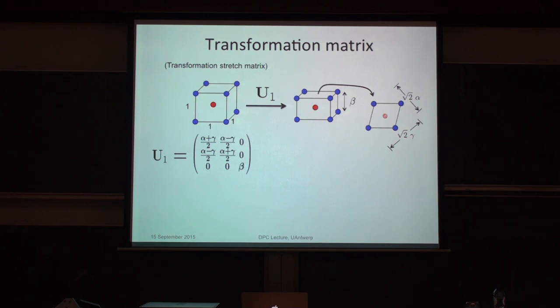In this case it's a shortening on this vertical axis, and the top face, which is a square here, becomes a rhombus here. And if you choose units so these edges are one, there are three parameters here, alpha, beta, and gamma. And this U1 is the matrix of the linear transformation in the cubic basis that takes this to this. So that's the matrix which describes the linear transformation. That's the transformation matrix or transformation stretch matrix. And I'll be talking about this matrix.